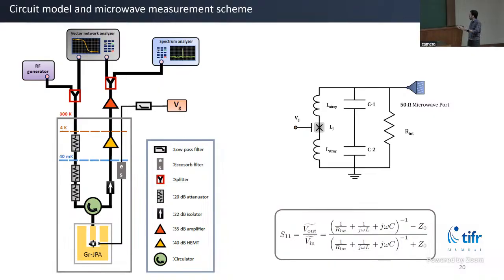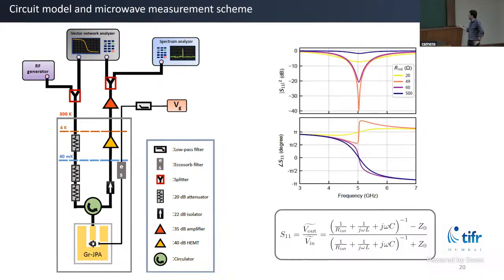And in experiment, we look at the reflection of microwaves, which is very similar to optics, where you look at reflectance or transmittance of optical signals. Here we look at reflection of microwave signals. That basically depends on the impedance of the circuit. Wherever there is impedance mismatch, the signal reflects back at that resonance frequency. This is a plot of this mathematical relation. If your resonance frequency is 5 gigahertz, you will see a phase change at that point. The phase of the reflected signal will change from plus pi to minus pi at the resonance frequency.